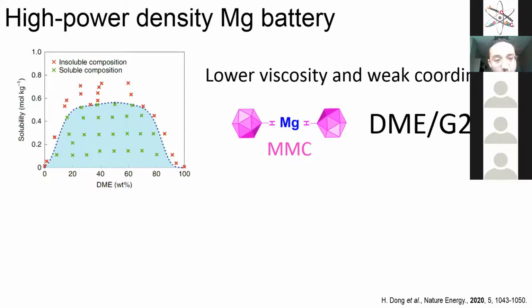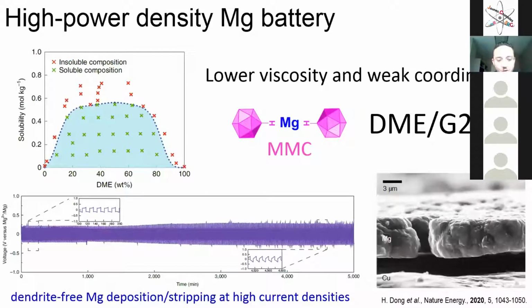So thanks to this hard work, they found an electrolyte formulation based on what we call MMC as a magnesium salt that you dissolve in a mixture of solvents, DME, dimethoxyethane, and diglyme. So if you use this electrolyte, you can have what we call a good deposition and stripping of magnesium. And here you can have a high stability of this. And then, as you can see on the right image below, you have no magnesium dendrites growing. So you have a homogeneous deposition and stripping, and you can always do this at high current density. And this is very, very important because you are going to see in the next slide why.